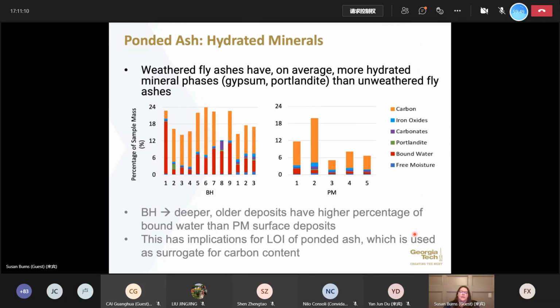So if you look on the left-hand side here, this is our borehole sample. So these are ashes which have been aged for maybe 30 or 40 years. So they've been out in the field for a very long time. And if you look closely at that, the red bars that we have here at the bottom are showing bound water. So the deeper, older deposits have a very high percentage of bound water, which are present in the mass of the ash.